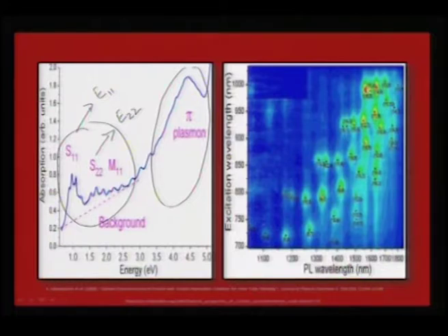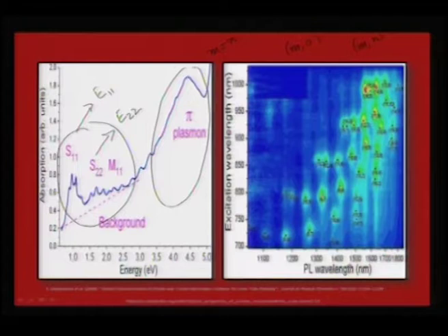Here again we see the profile of the excitation wavelength versus PL wavelength. As you would see here, these are plotted against the indices m and n. Whatever numbers you see here show that for m minus n being a multiple of 3, you do not see any photoluminescence, neither for m equal to n. The values in the parenthesis clearly tell us what sort of orientation of the nanotubes is going to be effective for photoluminescence. But the good news is that carbon nanotubes show a very strong photoluminescence, though it is also dependent on the chirality. So, depending on that we can map the photoluminescence response.